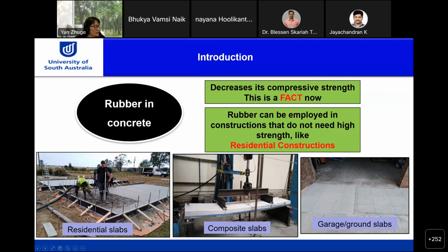These photos show the construction procedures for the 2 concrete slabs we constructed using commercial contractors. We constructed the 2 slabs side by side. One is normal reinforced concrete, and the other one is crumb rubber concrete. We have also done a lot of testing of composite slabs in our lab, and we also applied some crumb rubber concrete at our laboratory entrance as a ground slab. On this side is normal concrete, and on the other side is crumb rubber concrete.